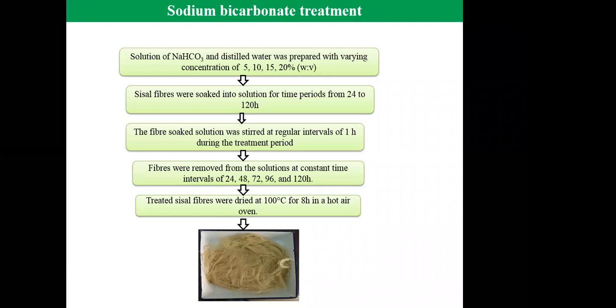So this treatment is not health hazardous. Because of this nature, we prefer this eco-friendly treatment. There are some steps which I have followed for treatment. A solution of sodium bicarbonate and distilled water was prepared with varying concentrations. I have checked which concentration provides the optimum result.